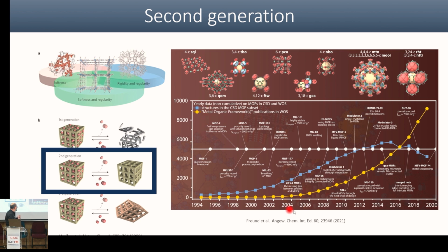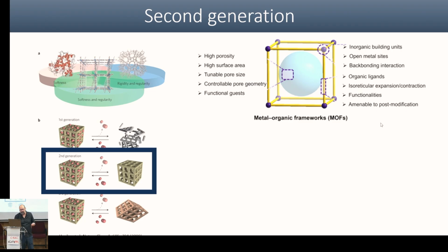And then here you can see the historical evolution of the field in terms of structure, crystalline structure reported, that is in the maximum and it's coming down. And we can say, okay, thematic is done. No, we have huge amount of MOF, okay, as you can see. And here is a change with ZIF and UiO-66 especially, that become stable to water, so material scientists come to the field and the number of publications related to this material start increasing. So we have a threshold there where it was out of pure crystalline topic, pure absorption, more related to material science. And okay, just we have high porosity, we have high surface area, we can tune the pore, we can control the pore geometry, we can change the inorganic unit, we can change the organic ligand and so on.